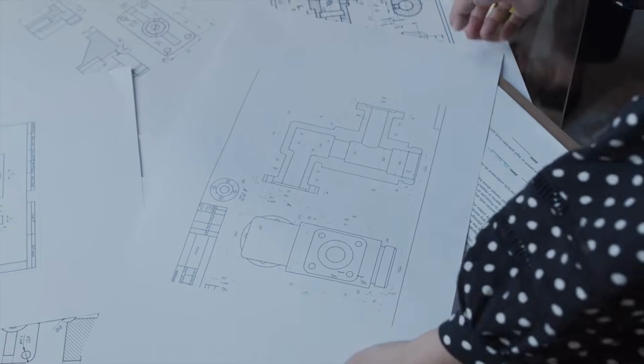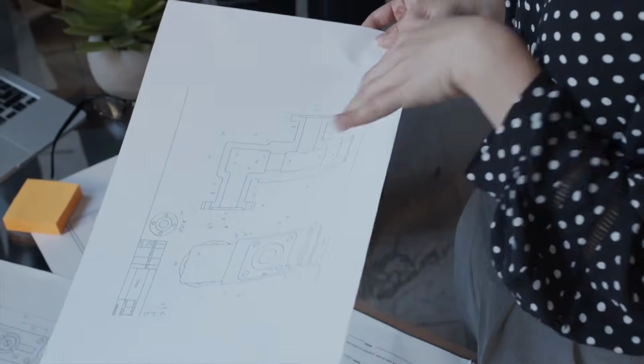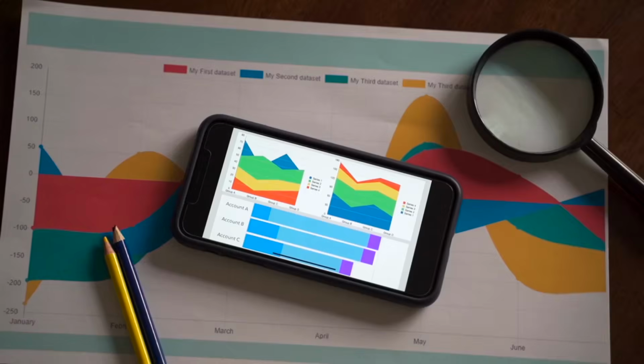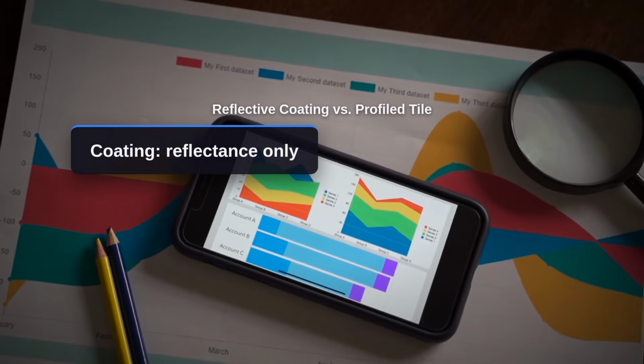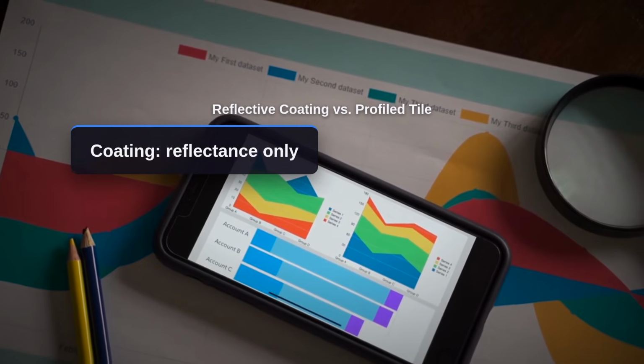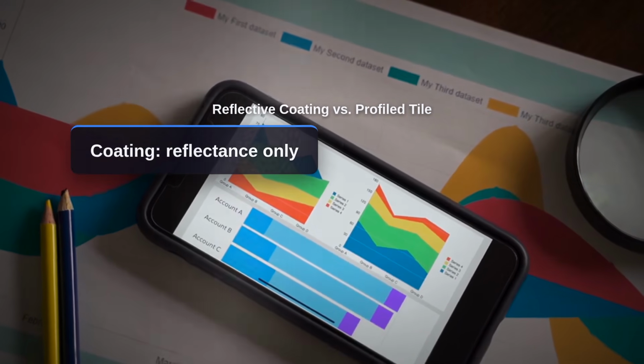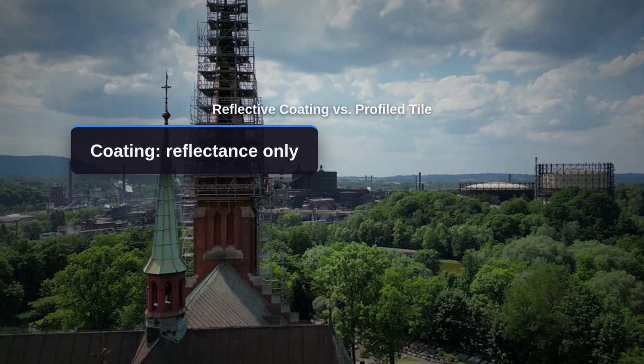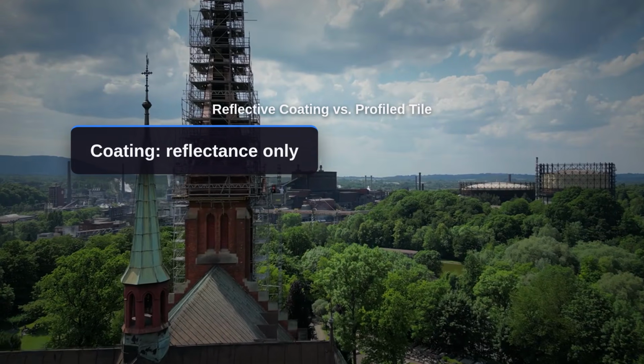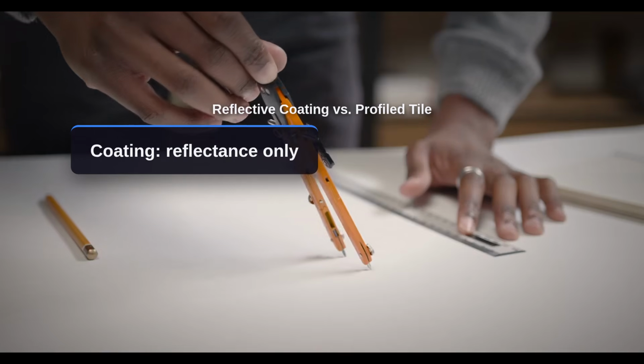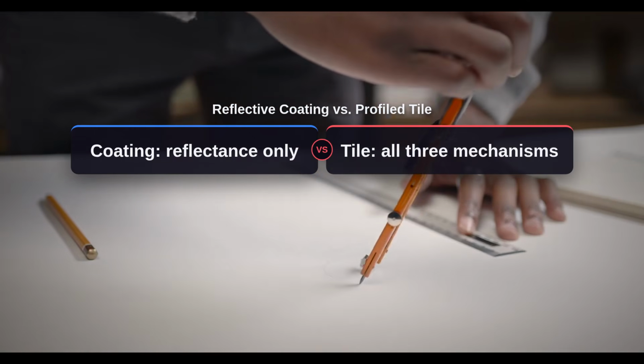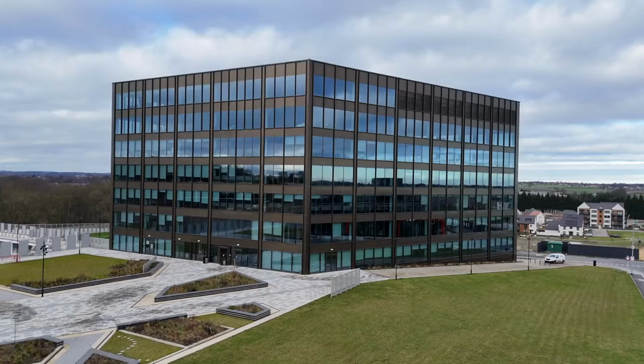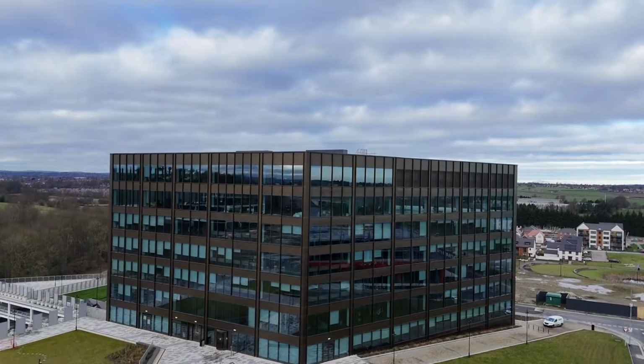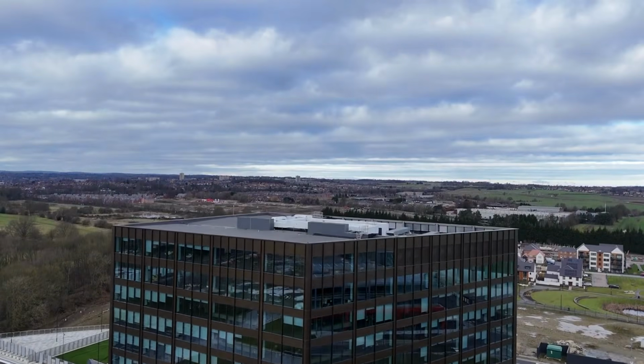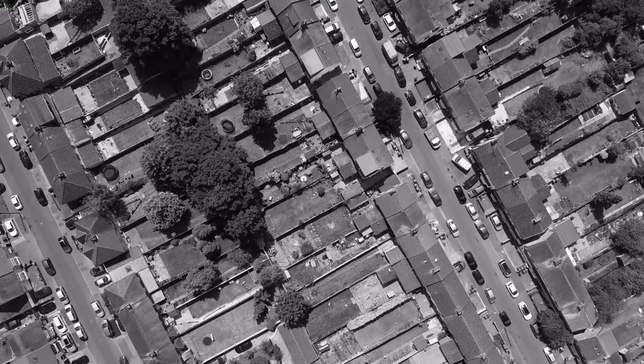But here is the critical distinction between reflective coatings and profiled tile systems, because conflating them is a common error in the green building space. A reflective coating addresses only the first mechanism, solar reflectance. It does nothing for thermal mass phase shifting. It does nothing for above-sheathing ventilation. On a flat roof, where there is no air gap and no mass, you get the reflectance benefit and nothing else. On a hot climate-pitched roof, where all 3 mechanisms could theoretically work together, a coating on flat asphalt is leaving 50 to 60% of the available passive cooling potential on the table.